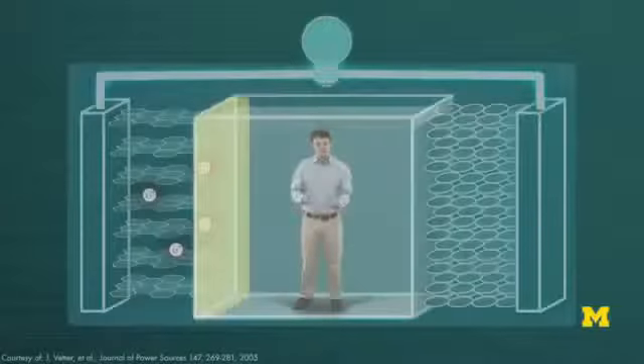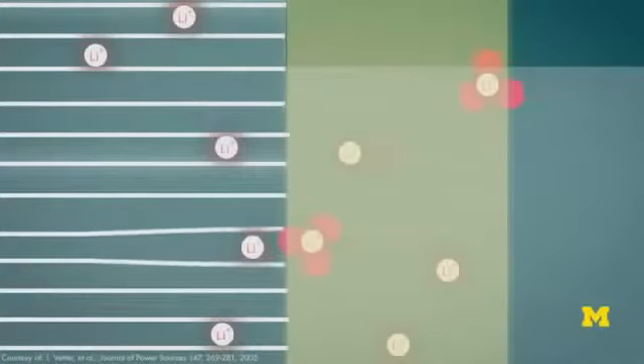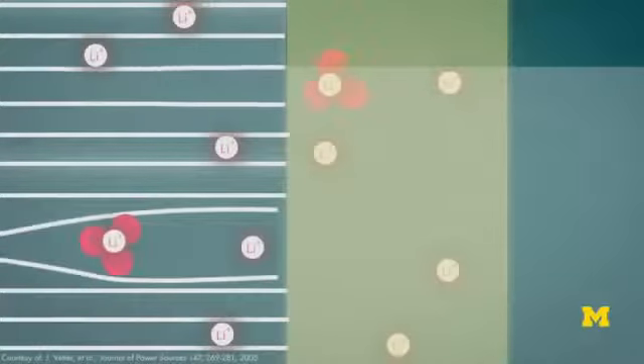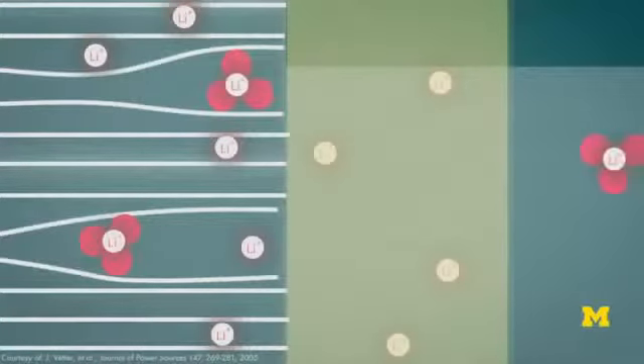So that's not the whole story. Other bad things can still happen, and this would be associated with the formation of new SEI in the course of operating the battery. And in these batteries, because we're intercalating lithium, there can be some small swelling in the carbon particles associated with that process. We can also insert lithium that's been bonded or interacting with solvent molecules. This is what we call co-intercalation of lithium and solvent. That tends to exfoliate these graphene sheets, which would expose new parts of nascent carbon material, which could then further react with the electrolyte and generate new SEI. So SEI cracking followed by the formation of new SEI, with some of that old SEI dissolving back into the electrolyte. These are all problems which at the end result in creation of new SEI over time.